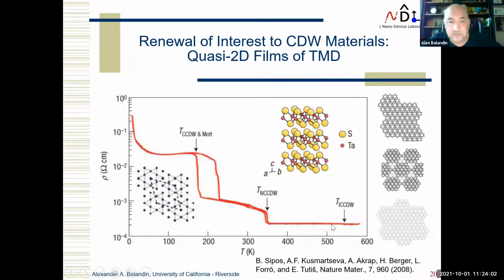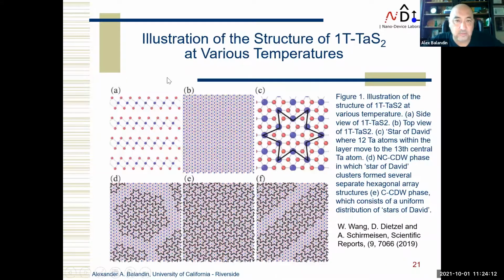Okay. And of course, like physicists, we're mostly interested in this low temperature transition. It's probably easier to understand the physics there, etc. And I'm sorry, if you look at this, I took it from one paper I saw online. This also clarifies the structure a little bit. This is 1T tantalum disulfide from the side view, you have these layers and then the van der Waals gap. This is the top view. And when you go through the transition, you have distortion in the lattice, where 12 tantalum atoms move slightly toward the 13th atom, which forms a sort of Star of David.